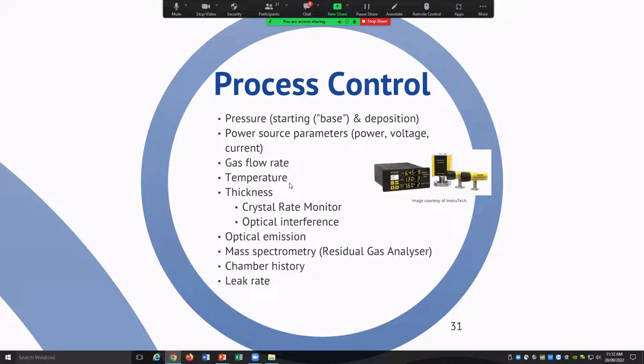If you've got a plasma, then you can look at that plasma to see what excited species are in it, and that's the optical emission. So optical emission spectroscopy is interesting. Or you can even do mass spectrometry, so knowing exactly what's in the residual vacuum, what's left behind once you've pumped it down, how much water is in there, is there any oil from the vacuum pump, or how much argon, how much oxygen I have in my process. Whoever's used the chamber before, what's happened to it is important as well, and then leak rate. So all chambers leak. What's acceptable is something that you need to establish and then make sure that you're below that leak rate.